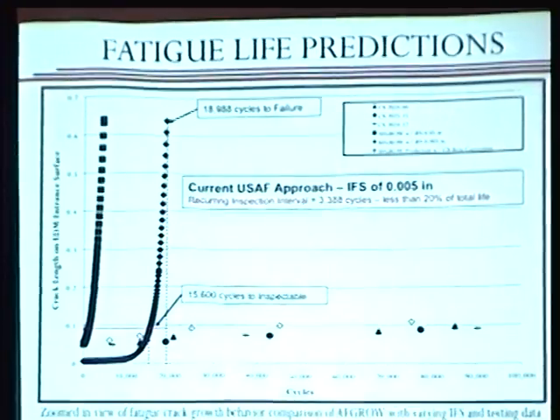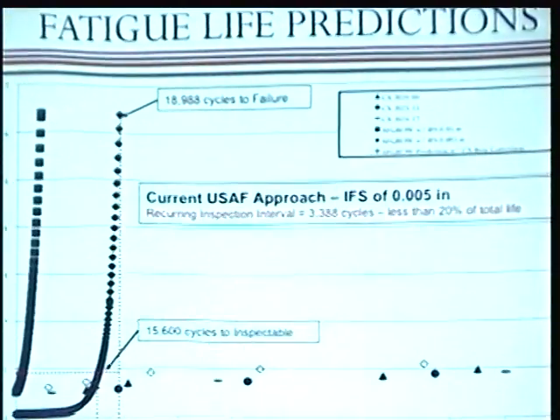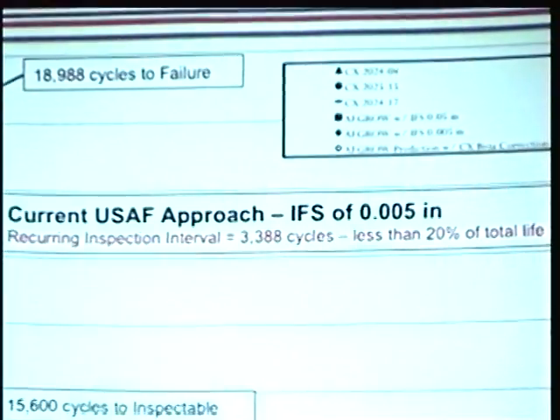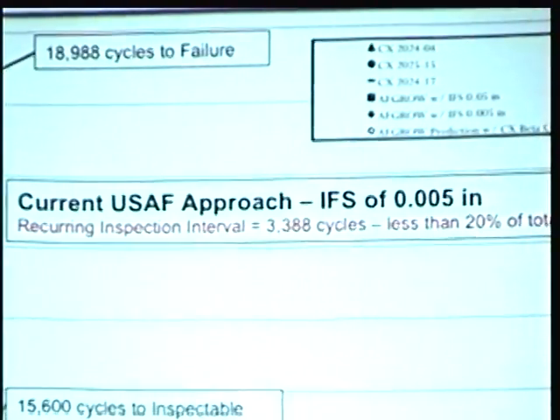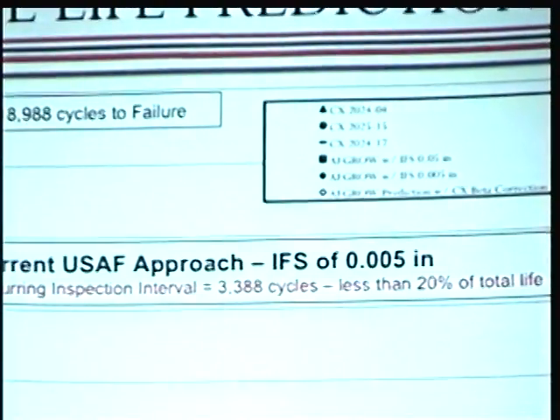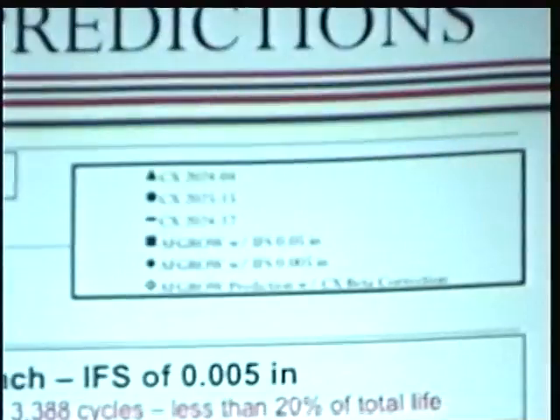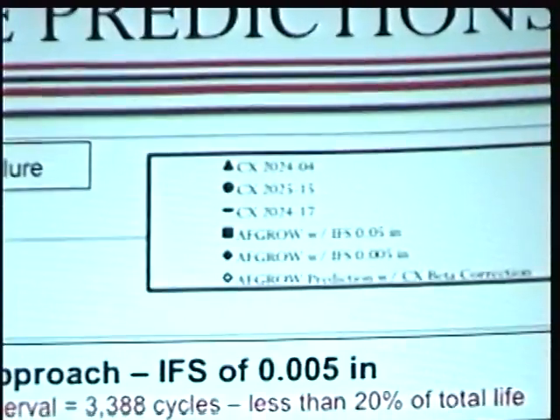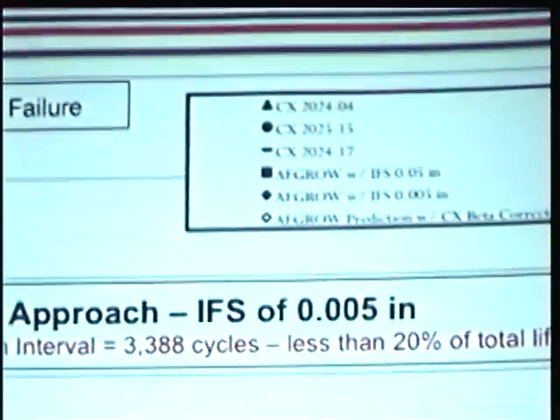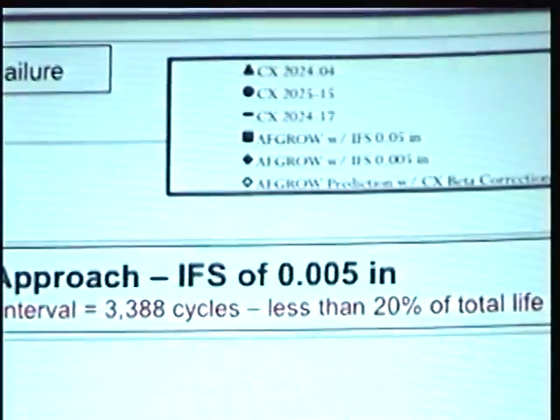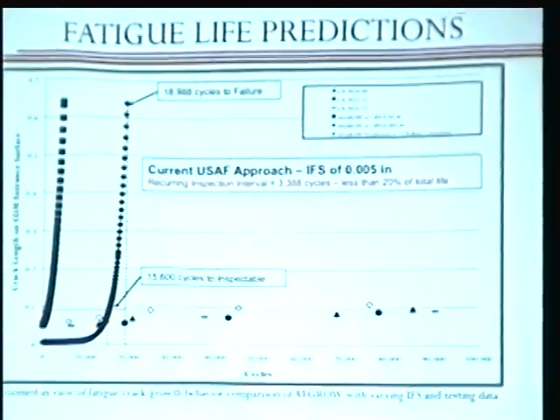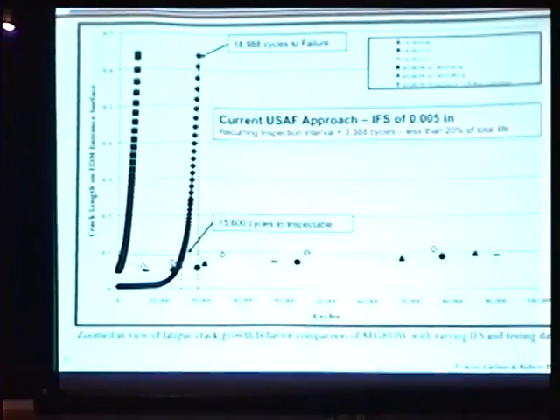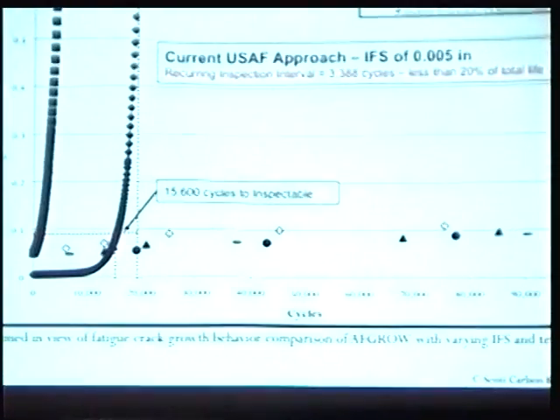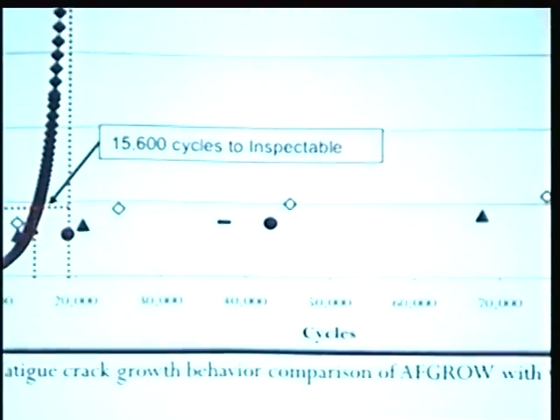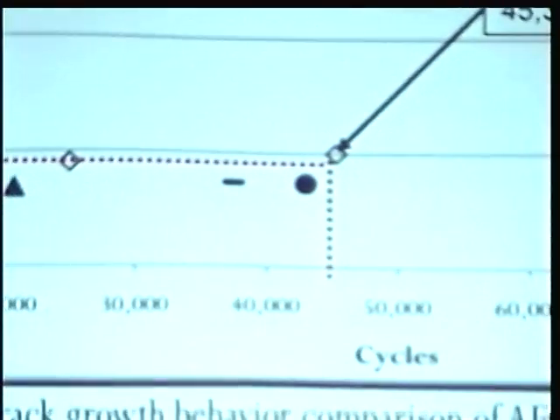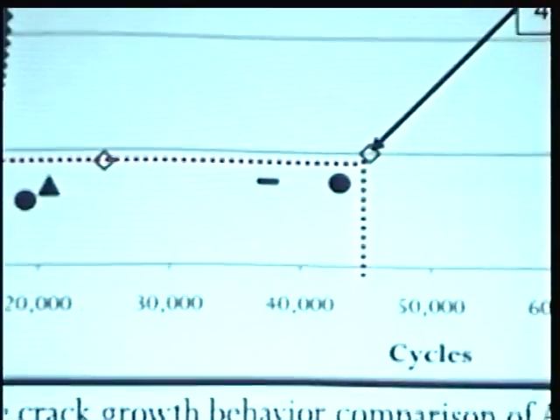So really, even though there's 40 and something thousand cycles of life in this component, based on our current methodology, we show 15,600 cycles that, based on analysis, that's how long it's going to last from our detectable flaw size to critical. So really, we're stuck in this little teeny box. This is how we have to inspect. We've got to keep bringing it back to the depot, keep bringing these jets back, keep taking them apart, and continue to do inspections, just because we don't really understand what's going on as far as being able to predict the crack growth.